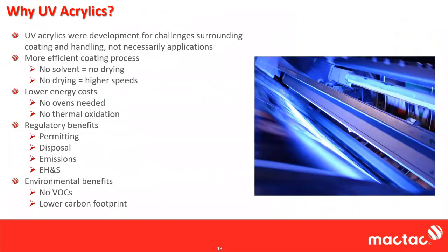So if they're so similar, why UV acrylics? Why did the UV acrylics come about? The first thing I mention here is that UV acrylics really came about mainly because of the processing and handling, not because of any shortfall in performance properties, anything that you would see at the end use application. So we're seeing UV acrylics because they're more efficient in the coating process. No solvent equals no drying equals higher line speeds. The drying of the solution carrier, the solvent or even the water if you're talking emulsions, will always be the rate limiting step when you're talking about solution-based adhesives. If you eliminate the drying, you certainly can move a heck of a lot faster in terms of your line speeds. You're also lowering your energy costs.